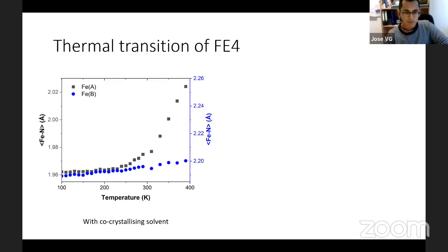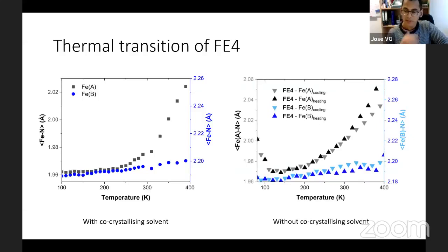However, when I carefully remove the solvent, I observe some small changes. Of course, when you remove the solvent, there is a higher structural change, so there is more transition from low spin to high spin, or the transition occurs at lower temperatures. And this of course occurs the same here. But also, if you see, for example, these gray and black triangles at low temperature, around 100K, you see this reverse transition.